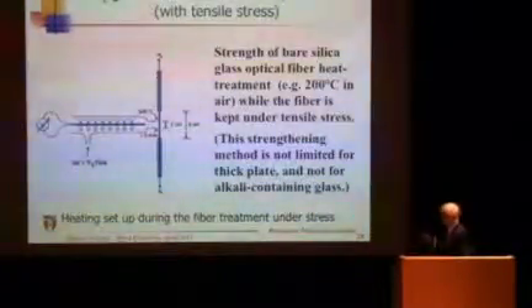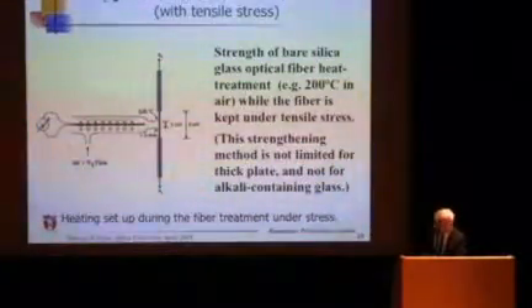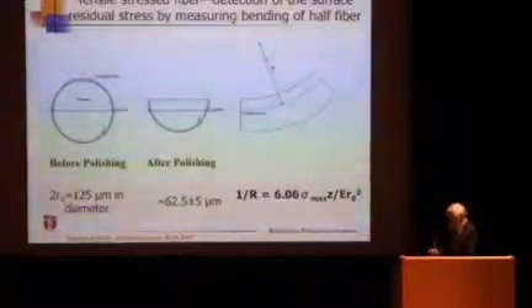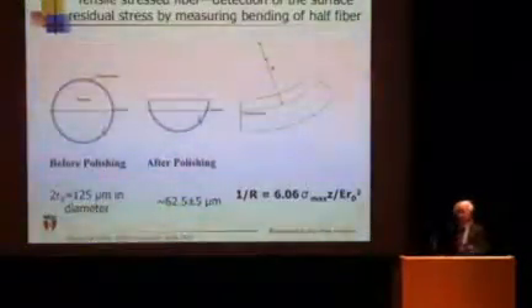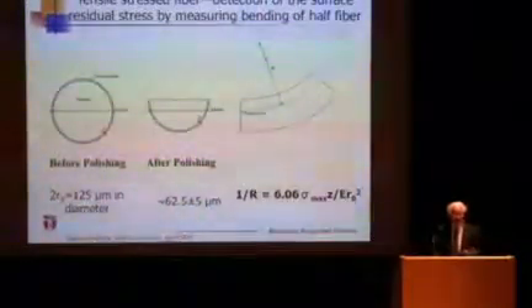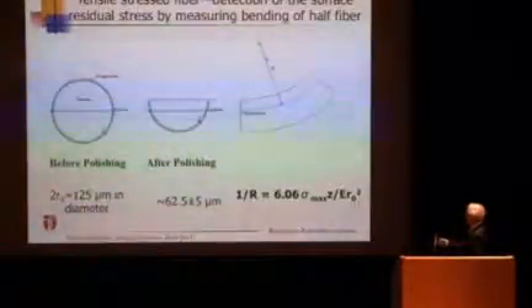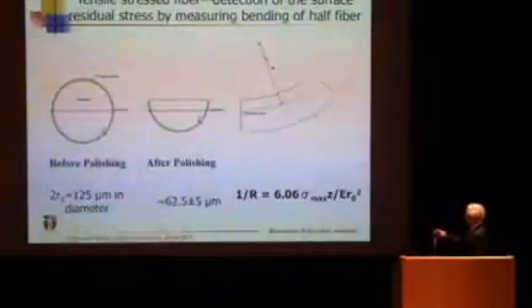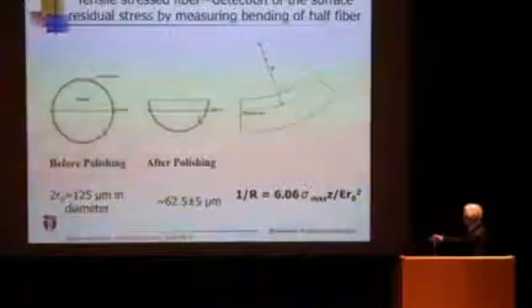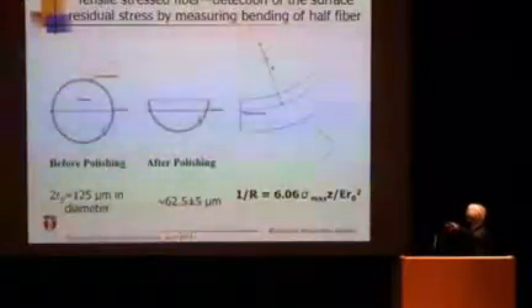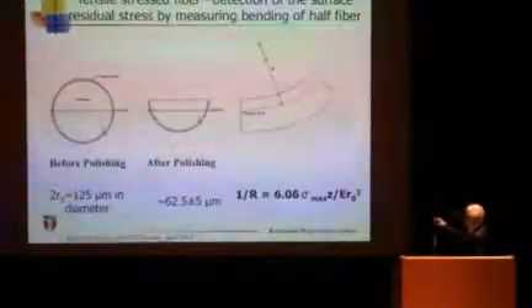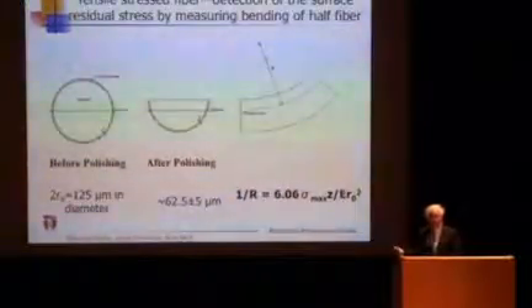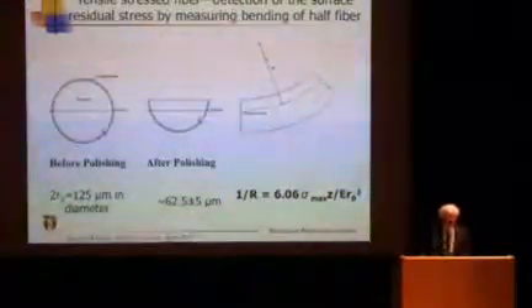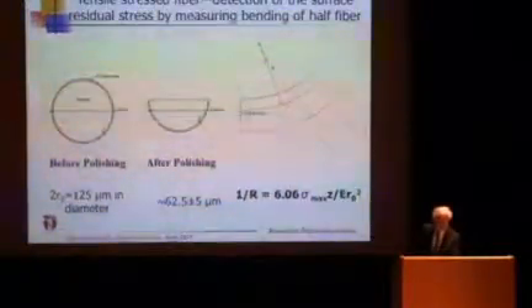And then we take that piece and test the mechanical strength. Just to show that a surface compressive stress is generated, we slice the fiber in half. And because of the compressive layer, the fiber should curve in this way. And indeed it does. So we know the compressive residual stress is produced.